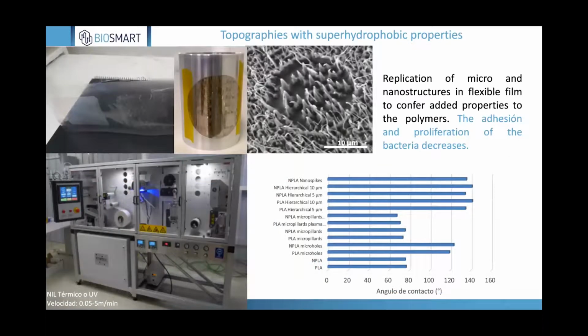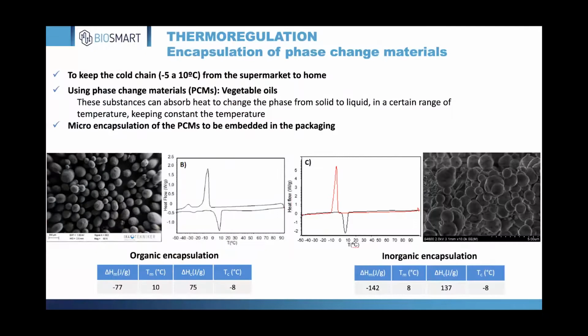Another technology that has been used also to modify the surface is the replication using physical nanostructuring of the flexible surface in order to confer a surface geometry that are able to reduce or decrease the proliferation of the bacteria. We have observed that it's practically possible to achieve super hydrophobic surface with very high contact angles using this process.